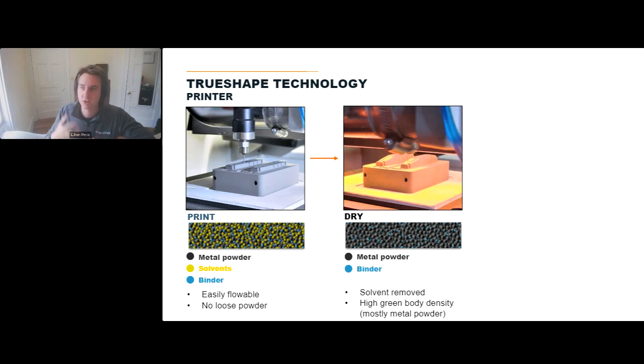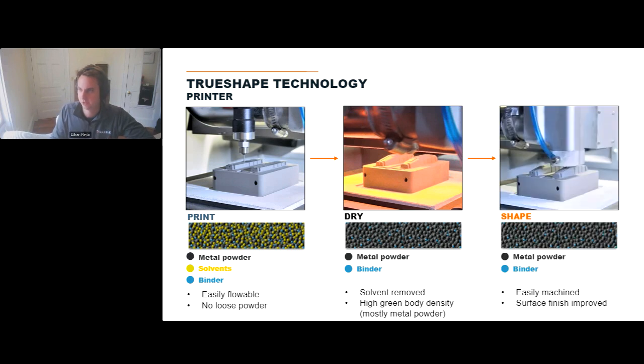The truth here is that the solvent's really only required to allow it to flow, to be viscous enough that it can be extruded. After we dry it, it's kind of densified a little bit, and it's more like a dense foam now. So we've gone from our toothpaste to sort of a foam, which is really critical for us because now we're able to machine it. So we actually build our printer inside of a Robodrill style CNC. It's a CNC that we retrofit to print our paste material, because every single layer we are printing, drying, and machining. So every single layer this is happening, and during that machining step, we're refining the surface finish, or maybe adding in some features that we weren't able to print because of the nozzle size or the layer height.